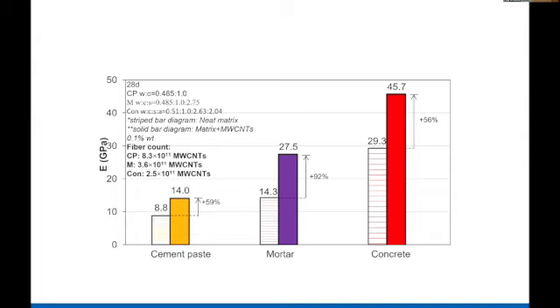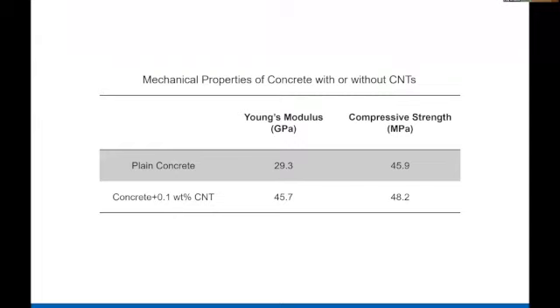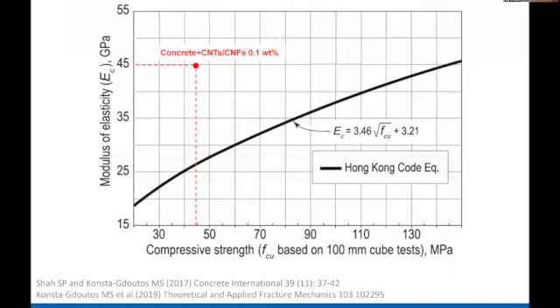So we tested many concrete specimens, and here is one set of results. If you look at plain concrete and the concrete at the bottom with 0.1%, there is not much increase in compressive strength, but a substantial increase in modulus of elasticity compared to plain concrete. So what does that mean? If you look at the chart I showed you before, when we add 0.1%, I get 45 gigapascal without increasing compressive strength. That's a substantial reduction in cement, and a gain in sustainability. So this is one of the important attributes of carbon nanotube.